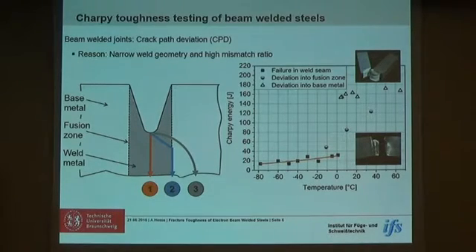If we think of Charpy toughness testing of beam welded steels, we shortly have to discuss that they behave differently compared to arc welded specimens or base metals. We have basically 3 failure patterns that usually occur. The one failure pattern which gives us information about the weld seam itself is a brittle fracture within the weld seam. And with rising temperatures, we usually can determine crack path deviation either into the fusion zone or into the base metal. The reason for this behavior is basically the relatively narrow weld geometry and the high mismatch ratio of the hardness between the weld seam and the base material.